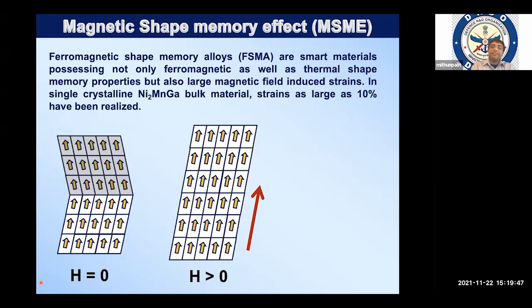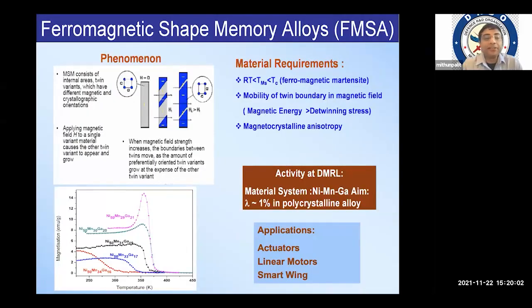Nickel manganese gallium is one of the very important materials, and people have reported up to 10% strain. However, the field application required to enact such twin boundary movement is very high. You can, however, reduce this further by making a proper single crystal, and in DMRL we are working on that. It has several applications: actuators, linear motors, and smart wings.